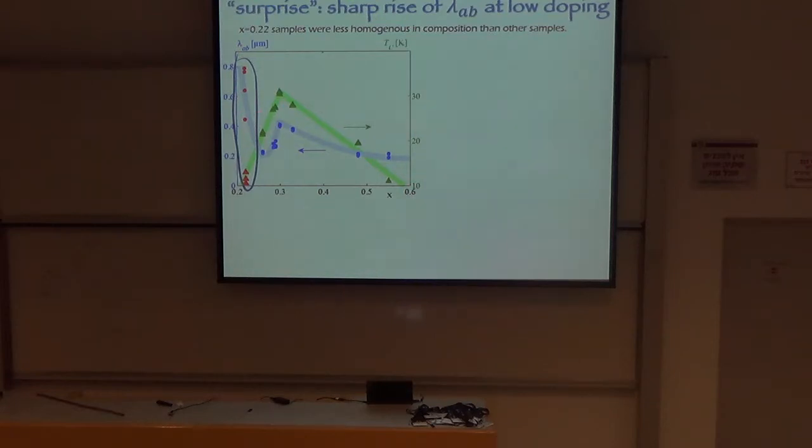The measurement is reproducible. If you repeat the measurement over and over again, this is not noise. This is just reflecting the fact that the doping is different in the area where we're doing the measurement. And what you can see now is that we can see the fate. Sorry, let's put it on this plot. You can see that these points behave very differently from the points I showed you before. They're kind of closer to what you would expect in a Uemura relation. I wouldn't make too much of it, but they sit here. The higher the TC, the smaller the penetration depth.